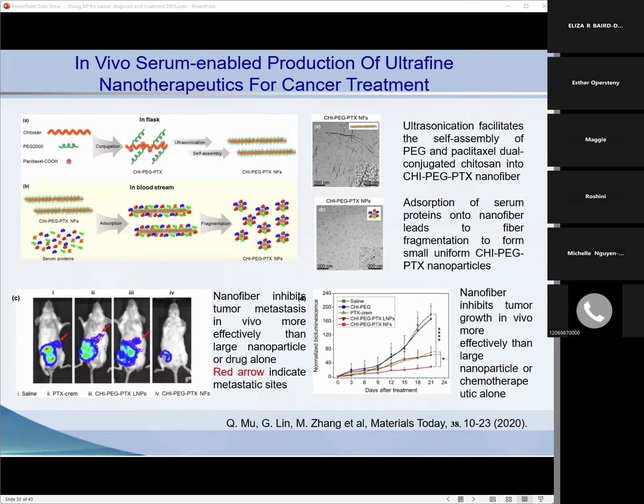So this is an interesting nanoparticle. We developed one nanoparticle made of chitosan, PEG, and paclitaxel. These materials self-assemble into a long fiber with a height of about 20 nanometers and a length of about 1 micron. We can control that. These particles are interesting because when injected in the blood, they break into 20 to 30 nanometer, very small particles. As you know, it's very difficult to make smaller nanoparticles, and the smaller nanoparticle is more efficient at reaching the tumor size. That's the motivation for us to design these nanoparticles. When they interact with the serum, these fibers can break into very small size.